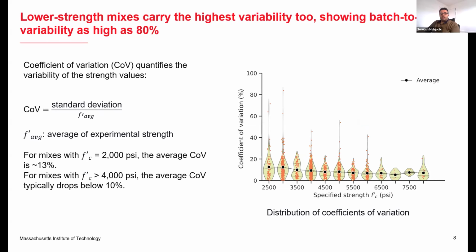Just as we saw with the over-design, lower strength mixes also exhibit the highest strength variability. We quantify this using the coefficient of variation, which is the standard deviation divided by the average experimental strength. These violin plots show the coefficient of variation, and it demonstrates that the variability decreases as the specified strength increases. For 2000 psi mixes, the average coefficient of variation is around 13%, with some batches showing variability as high as 80%. These extreme batch-to-batch variations across mixture codes create significant quality control challenges.